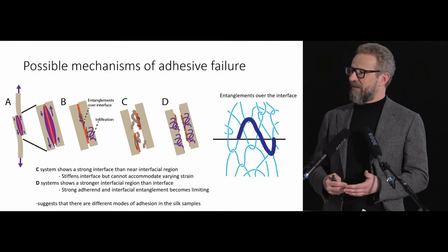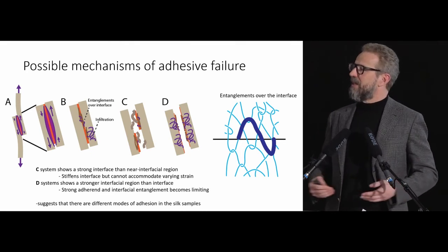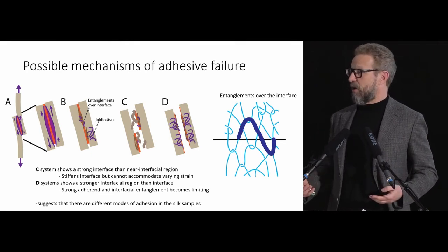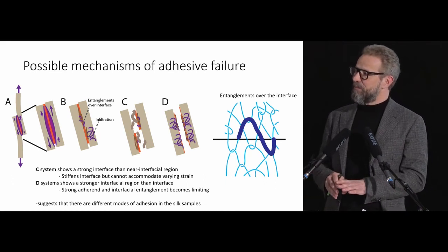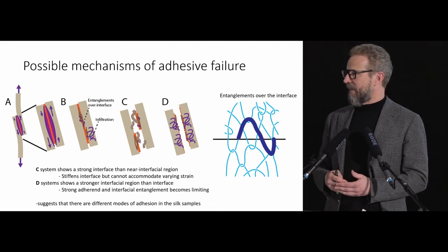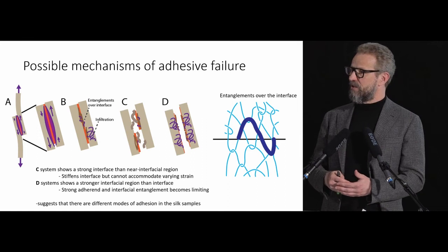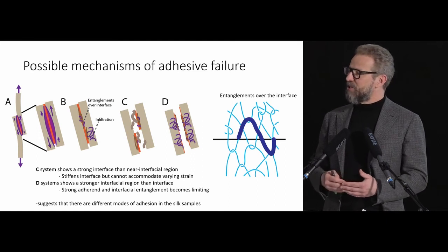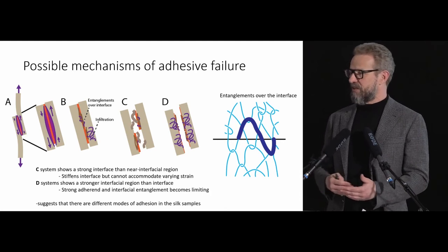Even though it binds well to the surface, it doesn't infiltrate the cellulose, leading to a large tear out when it breaks. The BSA goes well into the system, but it doesn't create entanglements over the surface. So it gives quite good strength to the sample and a clean surface, because it just goes in and doesn't cross the interface.